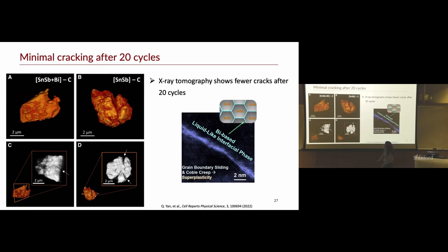And if you take just a single slice of the 3D volume, you can see there's a lot more cracking after 20 cycles in the particles without bismuth, versus there's just one crack we found in the particles with bismuth.